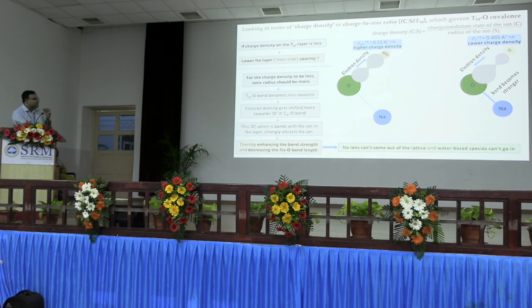So now how can I do that? If I select a cation combination in my transition metal oxygen slab which has a lower surface charge density, which means if I lower the charge to size ratio of the cation combination in my transition metal layer, I can have this scenario that my transition metal oxygen slab becomes less covalent, more ionic, and I can have a stronger sodium oxygen bond, and I can suppress the spontaneous sodium removal when exposed to air or maybe even water.